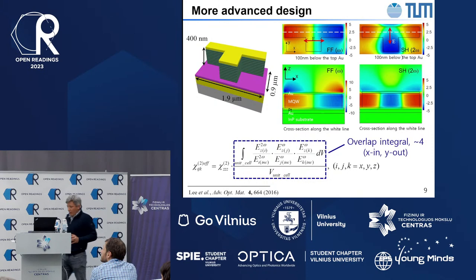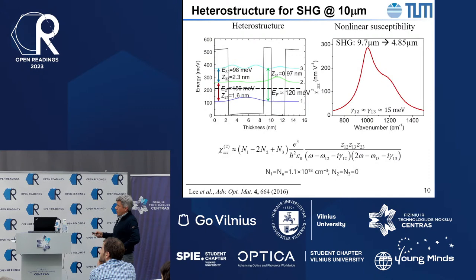And so we have this demonstration where we build this quantum well, we can design all this inter-subband transition, supply doping, and plot the nonlinear response function. And we already have 300 nanometers per volt or 300,000 picometers per volt, which is already a factor of 10,000 higher than that of typical nonlinear crystals. This is how the nonlinearity is going to look for this configuration. And we operate in the mid-infrared spectral range. So our input is roughly at 10 microns, and the second harmonic is at 4 microns.